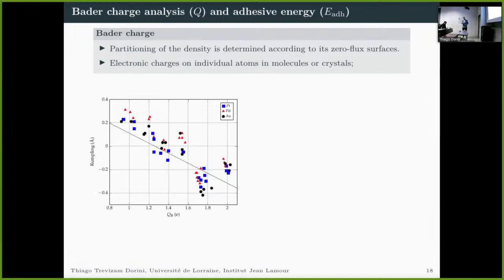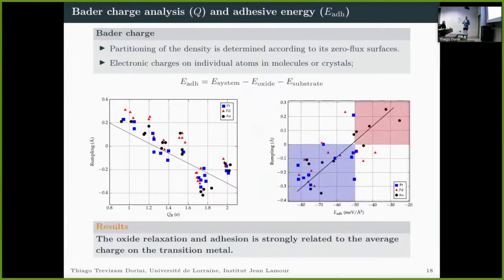And here we plotted the same rumpling parameter, the same structural parameter, according to the Bader charge on the transition metal. And we can see that there's a fairly linear relationship between how the oxide relaxes with the charge on this specific metal. And this also corresponds to an increase in the adhesive energy between the oxide and the metallic substrate. We have calculated adhesive energy with this equation. And you can see that the oxide bonds more strongly with the substrate when you have this characteristic on the rumpling. And we see that this all corresponds to how the charge is being concentrated or distributed in the transition metal.